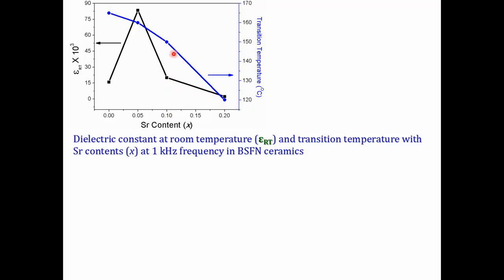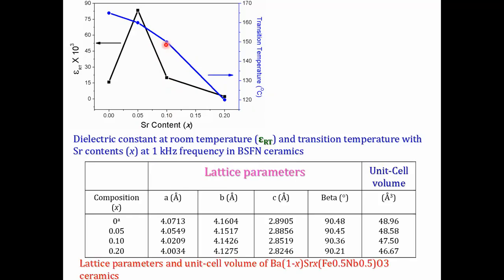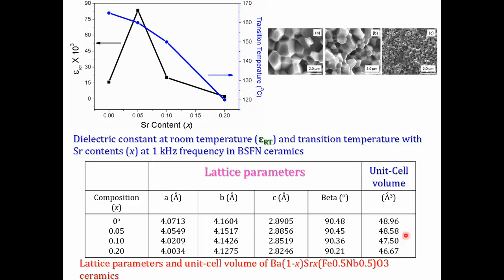So this is the explanation for the transition temperature decreasing. If you see the lattice parameters with doping, this is the unit cell volume: with x equal to 0, it's 48.96. When you dope with 0.05, 0.1, 0.2, this volume decreases. When the unit cell volume decreases, the energy required for the transition decreases. So the transition temperature also decreases, and the Curie temperature is achieved at lower temperature. This decrease in volume has been due to the addition of strontium. We have replaced barium by strontium, and strontium size is less than barium, so that has led to the decrease in volume size.